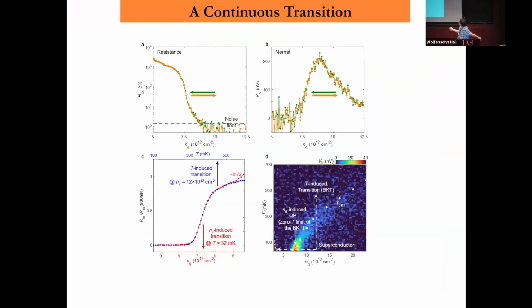And we also checked that it has to be a continuous transition because it's not first order. We do not see any hysteresis. If you ramp the density up and back, left and right, you never see hysteresis. Also, it's a KT, the end of the KT transition, right? So it's continuous. Experimentally, we cannot find any evidence of first order.